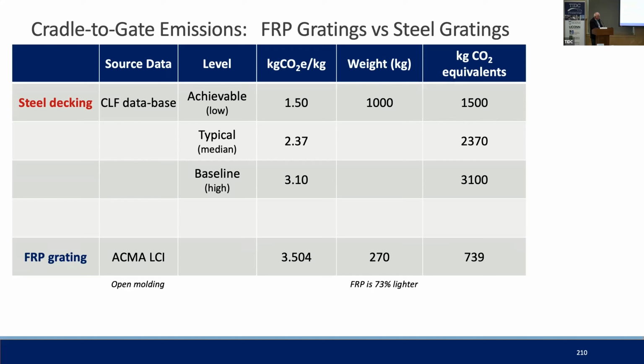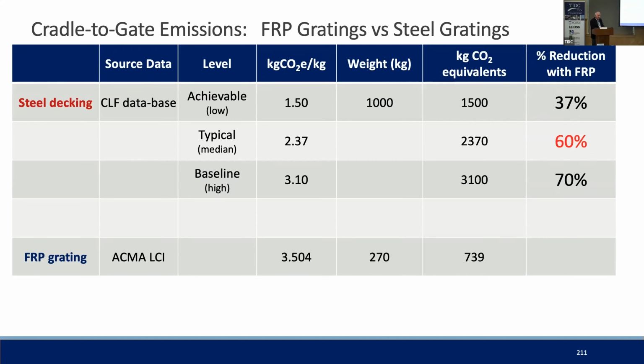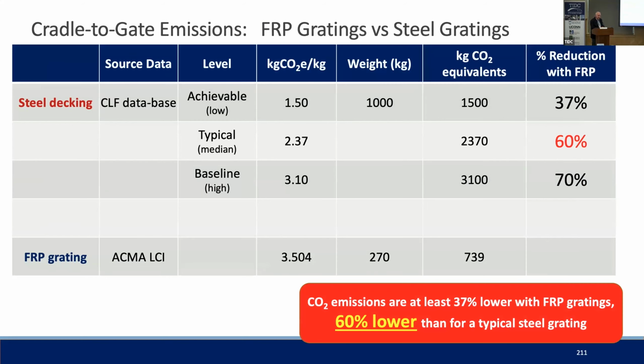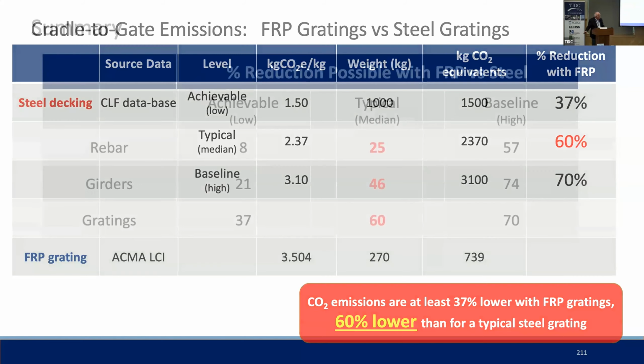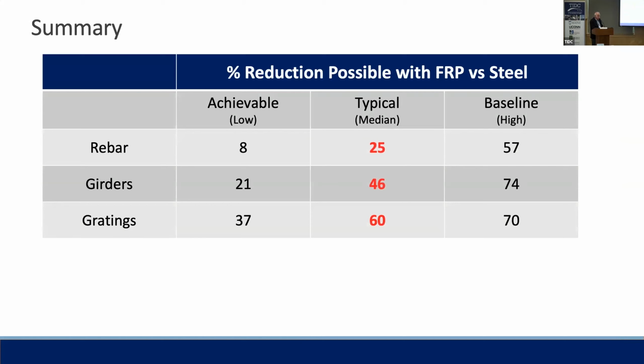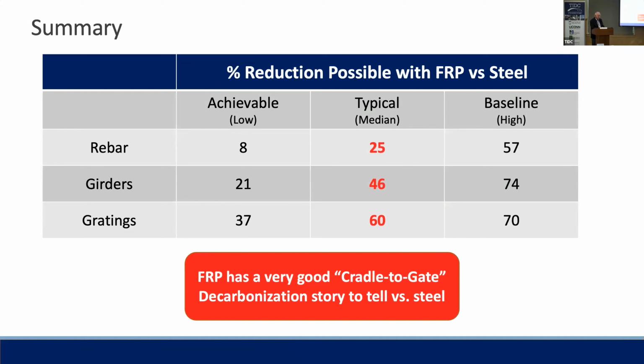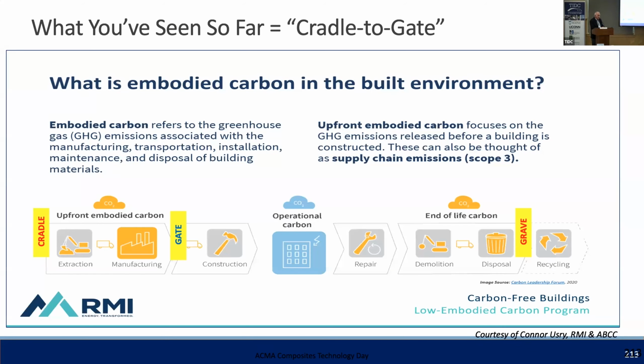Again, you do the math. FRP is 73% lighter. You get that 739. And the percent reductions with FRP are the highest yet. You've got at least 37% lower with FRP, 60% lower than for a typical steel grating. So to summarize the 3 examples, here is the percent reduction possible with FRP versus steel. For rebar, you're from 8 to 57%, girders 21 to 74%, gratings 37 to 70%. The bottom line from this data is that FRP has a very good cradle-to-gate decarbonization story to tell relative to steel.